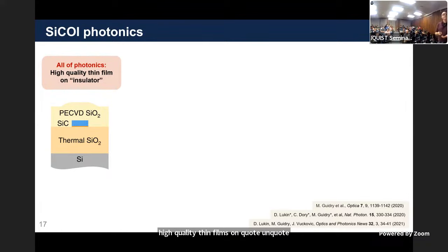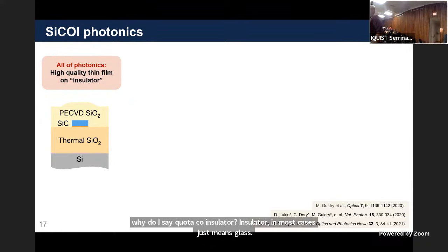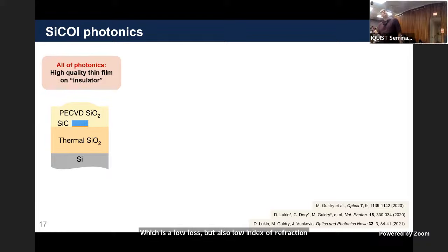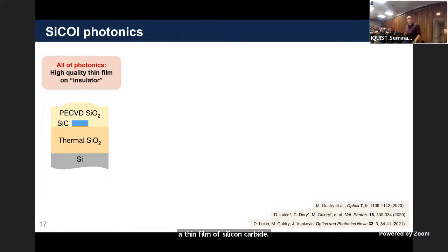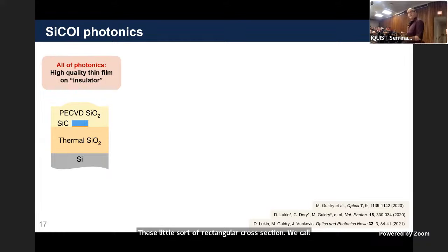So why do I say "insulator"? Insulator in most cases just means glass, SiO2, which is a low loss, but also low index of refraction optical material. Ideally what you would want is a thin film of silicon carbide on this low index of refraction material. Then you'd be able to etch, using standard nanofabrication techniques, these little rectangular cross sections, we call them waveguides. If you make this device starting from this thin film on insulator, what you actually have is a high index of refraction material surrounded on all sides by a lower index of refraction. So once you have this, by total internal reflection, you can guide light at the nanoscale in this sort of wire for light.